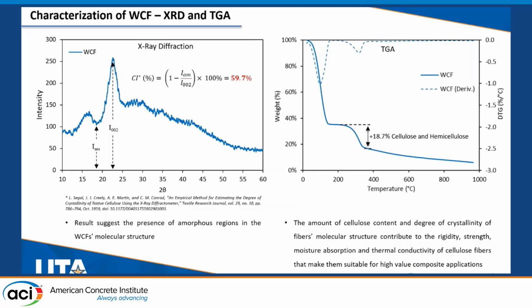For determination of crystallinity index, I used a peak height method using XRD spectrum that resulted in a CI equal to nearly 60%, suggesting the presence of amorphous regions in the molecular structure of these fibers. Also using TGA, we quantified the amount of cellulose and hemicellulose, which was nearly 19%.